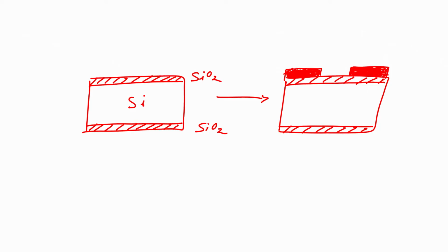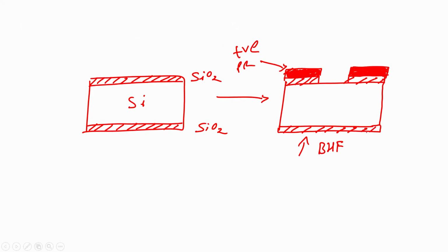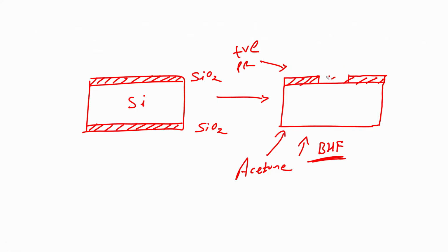If I dip this wafer, with let us say positive photoresist, in BHF, which is buffered hydrofluoric acid, what will happen? My silicon dioxide will get etched. In reality, the silicon dioxide from the back side will also get etched, because I do not have any protection on the back side. So, you have etched silicon dioxide by dipping the wafer in BHF. After this, if I further dip this wafer in acetone, what will happen? The photoresist that is here will be stripped off. Acetone is a stripper for photoresist.